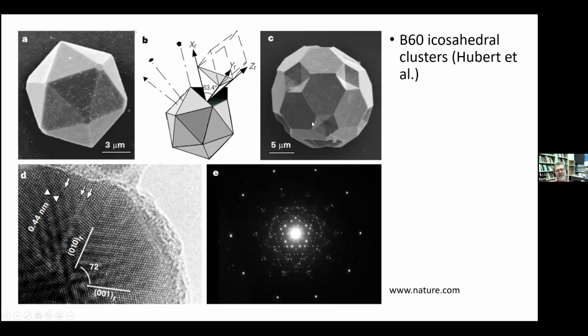It's interesting, and now it's also been observed for B4C, and even though these are small crystals, there's new papers where instead of using B2O3 as a flux, they've used boric acid, H3BO3, and they're able to grow crystals up to 1 millimeter, and they're still icosahedral. And instead of 5 GPa, they've gotten it down to 1 GPa. The real motivation for this would be that these particles could be great for grinding. That would be a commercial application, because